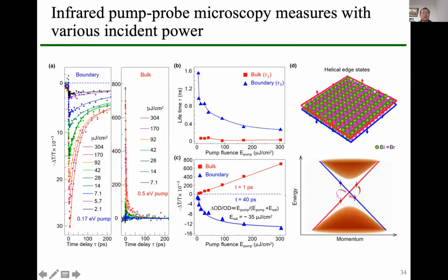So if we use different energy densities, we can see that the lifetime decreases as the photon energy density increases. This is true for the boundary and also for the bulk, because if we increase the photon energy, we will have more electron-electron coupling or Auger recombination, because the hot carriers are excited by the high energy density. But we can see that the long lifetime is still observed for the boundary, and the short lifetime is observed for the bulk.